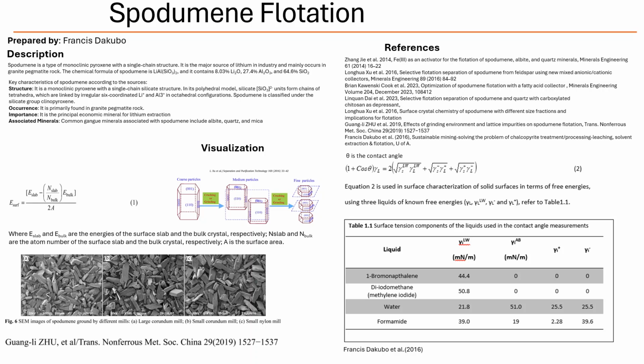Right, the DFT and molecular dynamics, they let researchers see these interactions. In a way, yes. They let us model how atoms and molecules behave at that interface between the mineral, the water, and the reagents. You can calculate surface energies, see how a collector molecule actually sits on the surface, figure out the binding strengths. Without having to do incredibly difficult surface science experiments for every single variable.